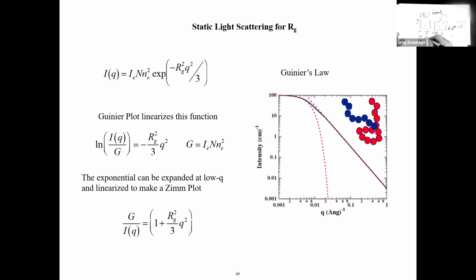The derivative is going to be 1 over N, then the concentration, and then the second virial coefficient, 1 minus 1/2 chi, by the Flory thing. That's going to be the change in pressure that happens when it fluctuates in and out. And that's what's giving you your contrast.